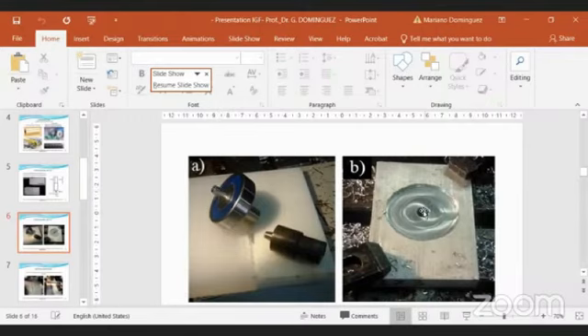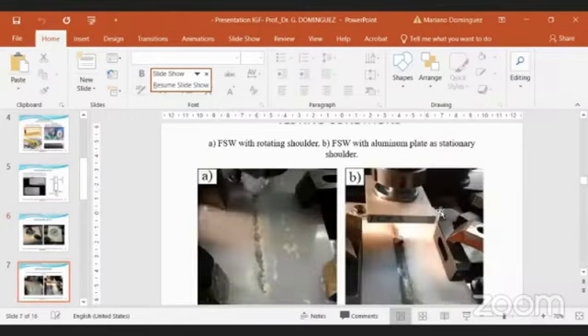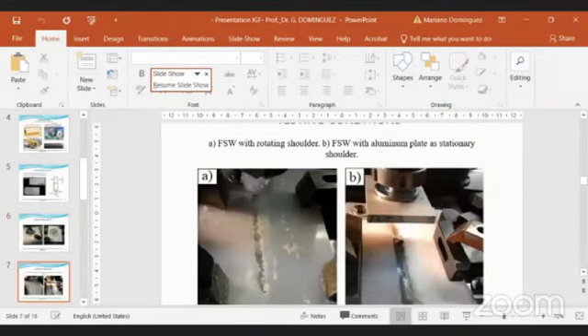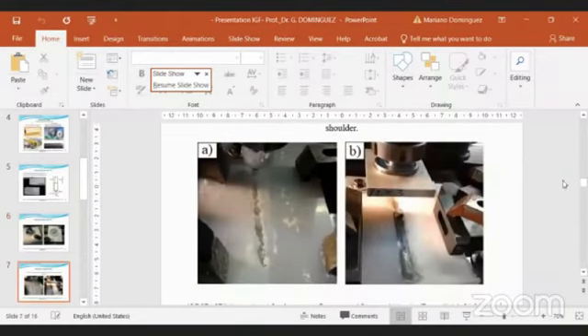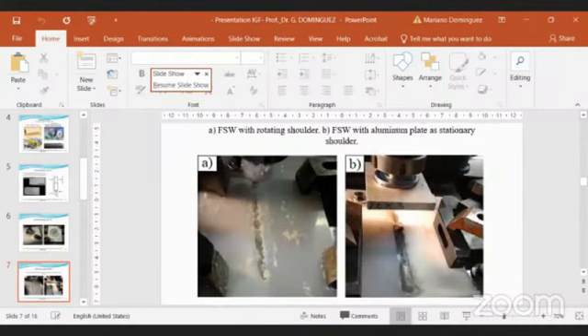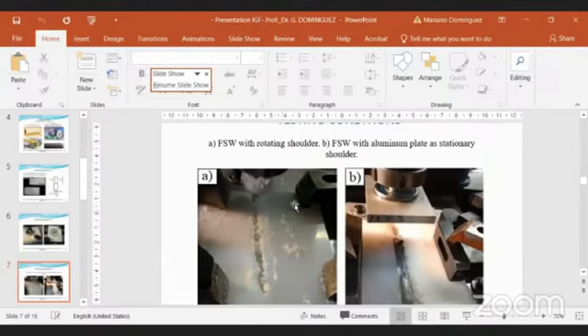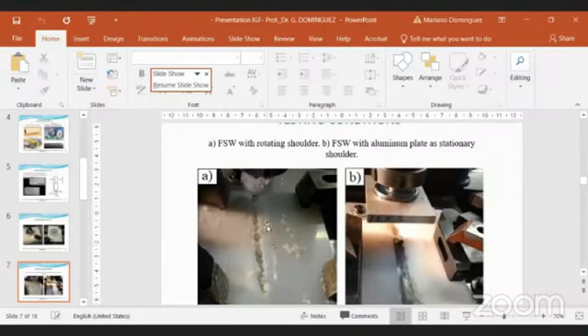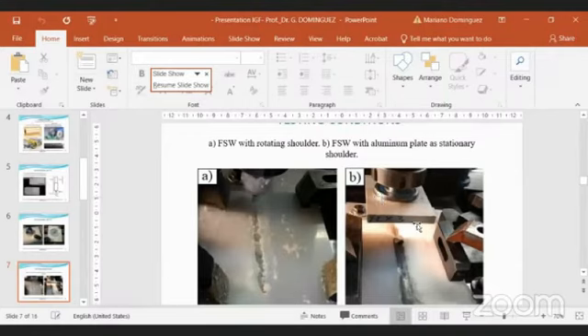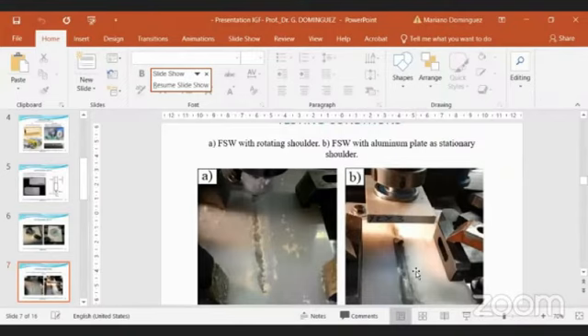The bearing is in an aluminum plate, allowing it to rotate only the pin, and the shoulder is a stationary shoulder. Here the first results: picture A shows the friction stir welding process without stationary shoulder, it's a rotating shoulder, and the welding is quite poor. In picture B we have stationary shoulder and the process of welding is improved greatly.